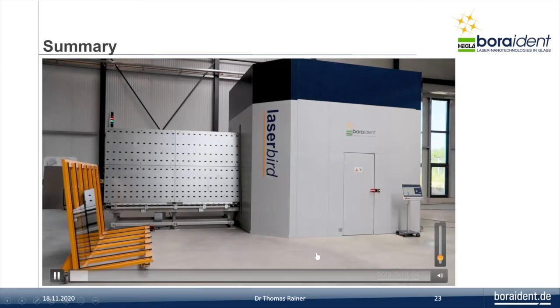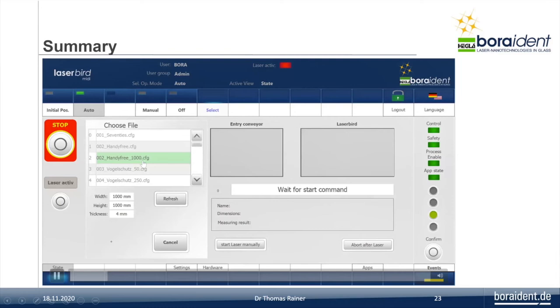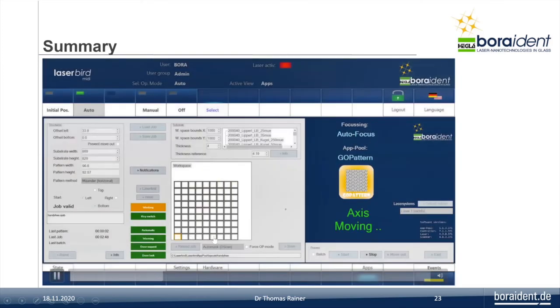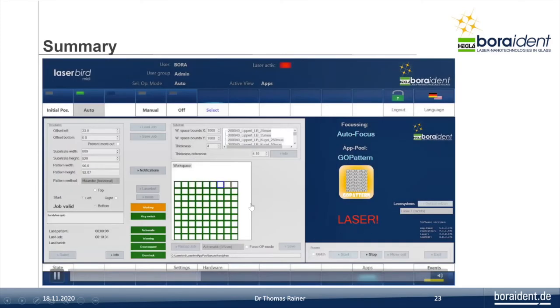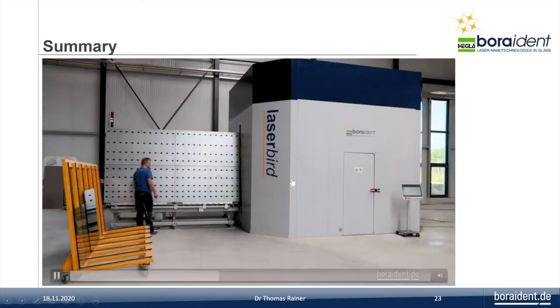Have a few insights. The LaserBird: you see here the HMI of the LaserBird, to choose the application. Put a glass pane on the entry conveyor, it goes inside the laser chamber, and then we have the patterning process step by step. Here you can see this is a patterning process. This is the glass pane itself, and on the blue line the laser is working on this pattern. And after it is finished, the glass goes automatically out of the system. So you can see here the glass pane goes inside the chamber.